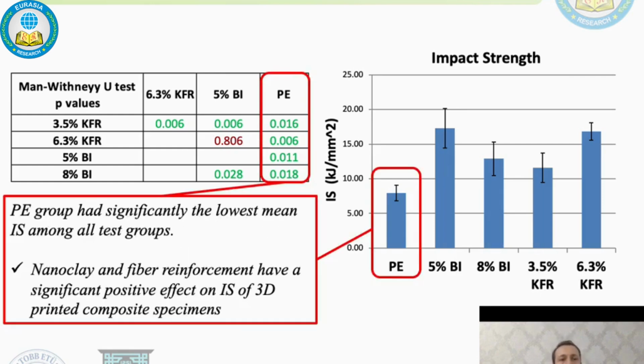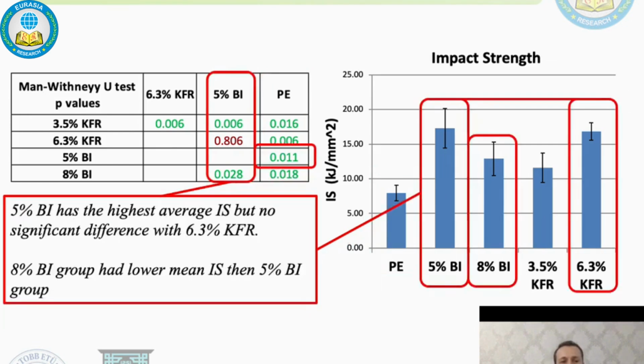Test results and discussion. As you can see, the pure epoxy group had significantly the lowest mean impact strength among all the test groups, and we can say that nanoclay and fiber reinforcement have a significant positive effect on impact strength of 3D printed composite specimens. The 5% base ink group has the highest average impact strength, but there is no significant difference between the 6.3% Kevlar fiber group and the 5% base ink group. The 8% base ink group had a lower mean impact strength than the 5% base ink group.